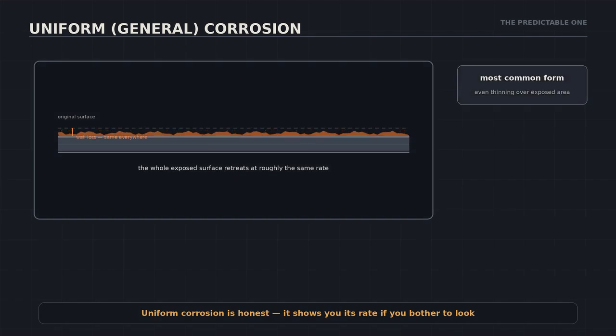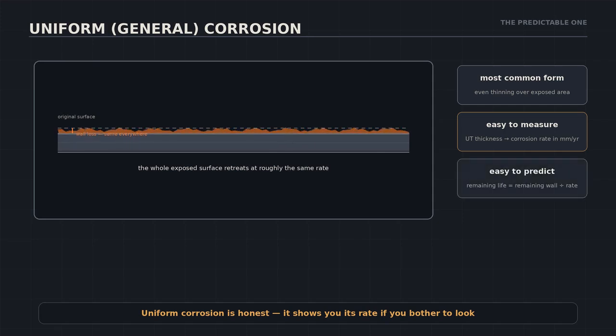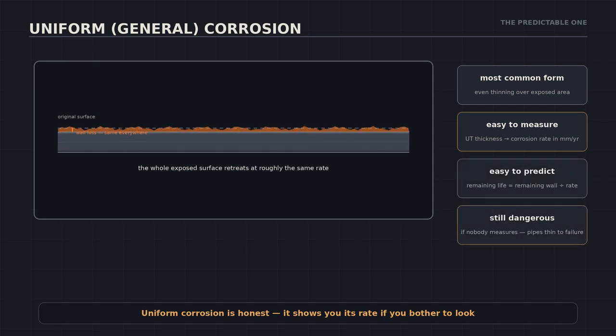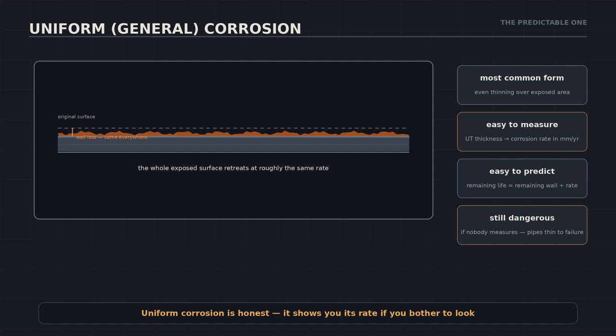Uniform corrosion is the most common and the most honest. The whole exposed surface retreats at roughly the same rate. That makes it easy to measure. Ultrasonic thickness readings give you the wall today, and repeated readings give you the rate in millimeters per year. From there, remaining life is simple arithmetic. The danger is not the mechanism, it is failing to measure it. Unchecked, a pipe quietly thins until the pressure wins.